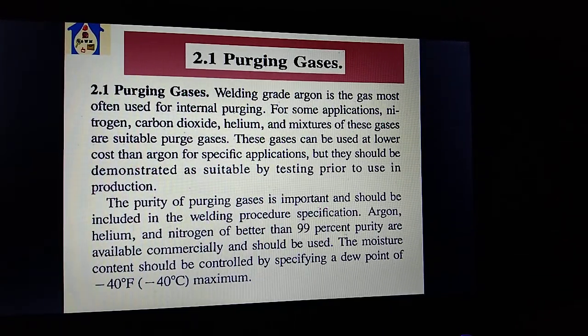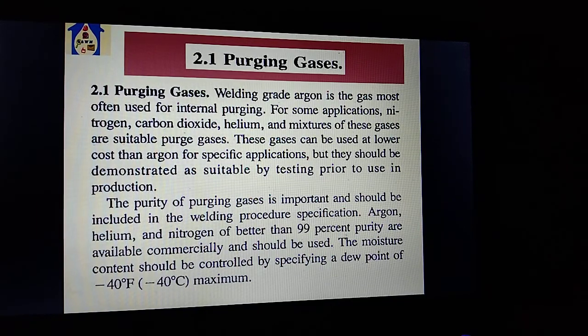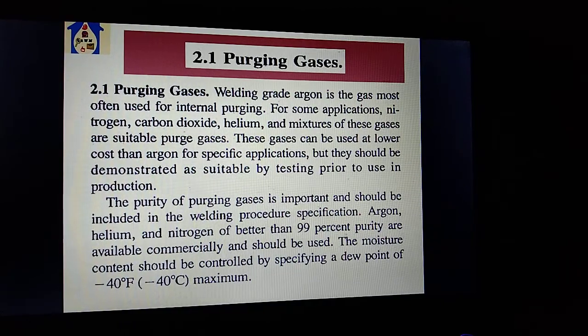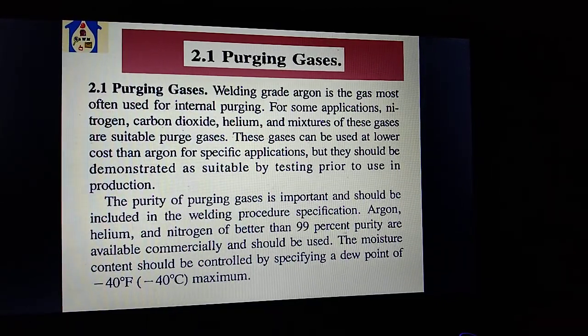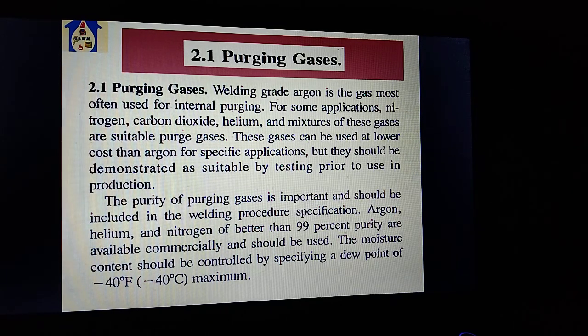Purging gas. Welding grade argon is the gas most often used for internal purging. For some applications, nitrogen, carbon dioxide, helium, and mixtures of these gases are suitable purge gases. These gases can be used at lower cost than argon for specific applications, but they should be demonstrated as suitable by testing prior to use in production. The purity of purging gases is important and should be included in the welding procedure specification.